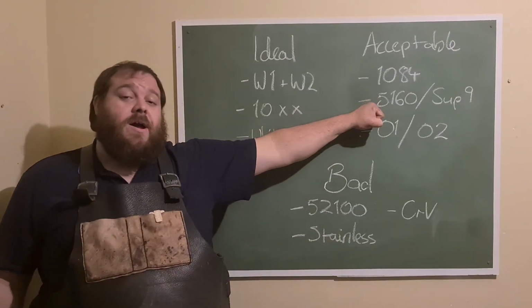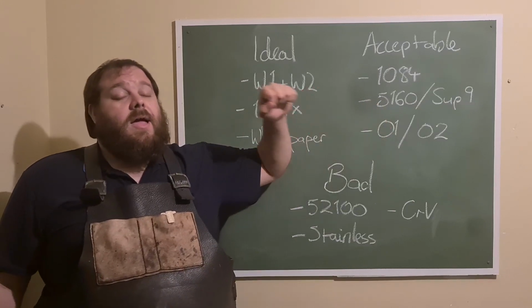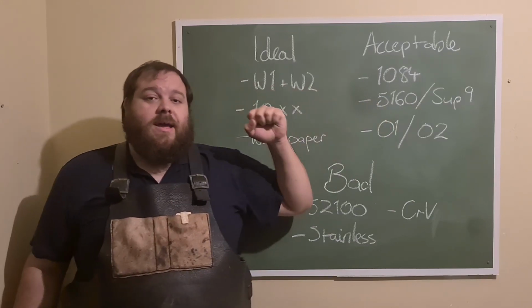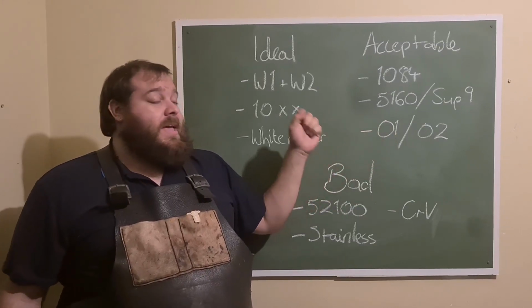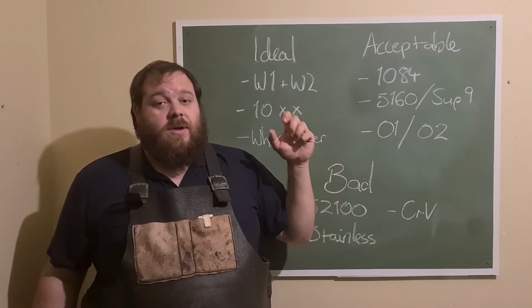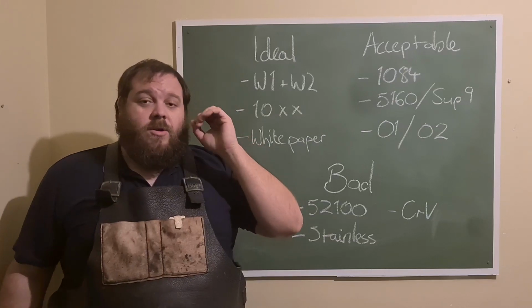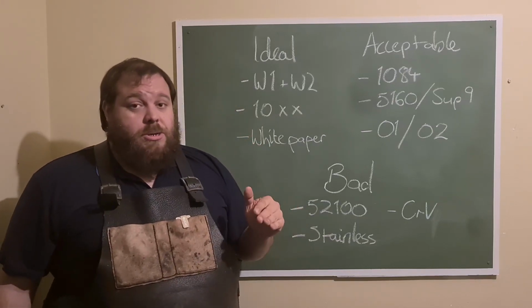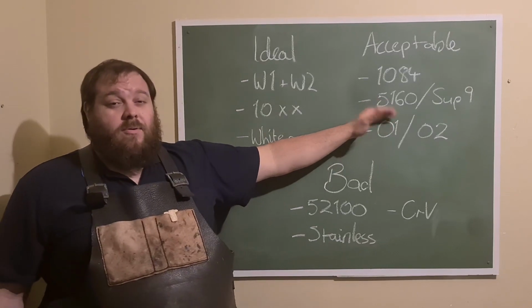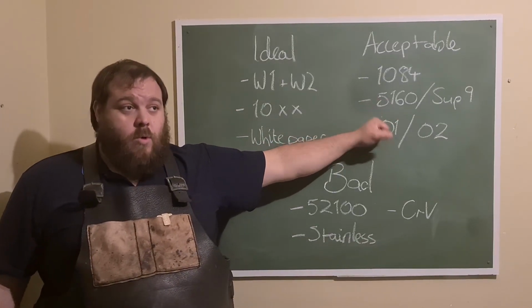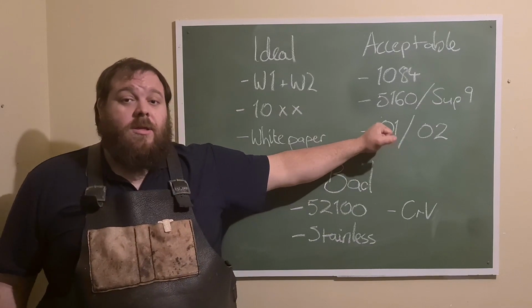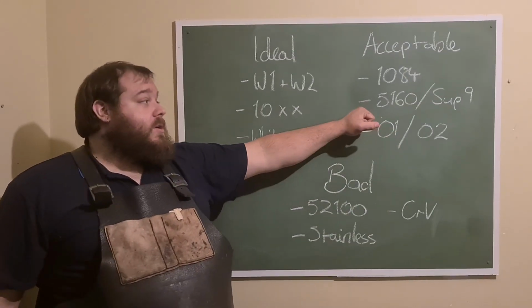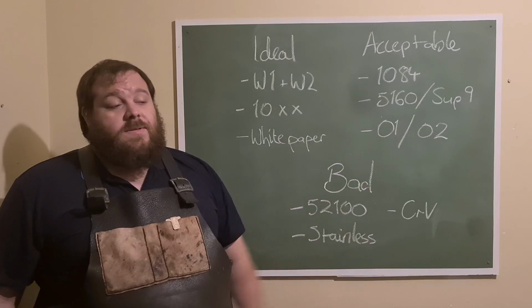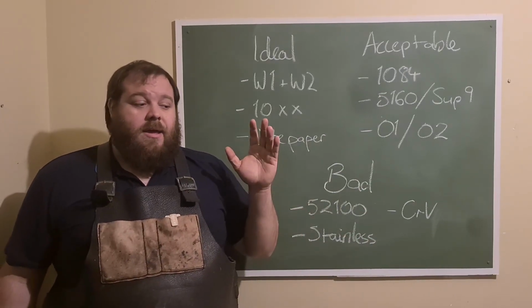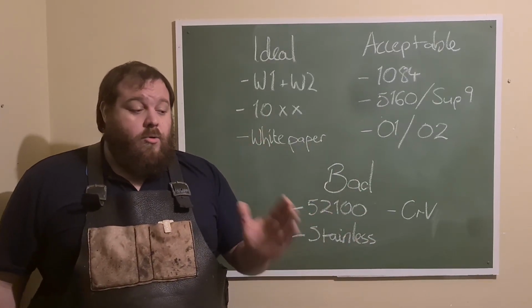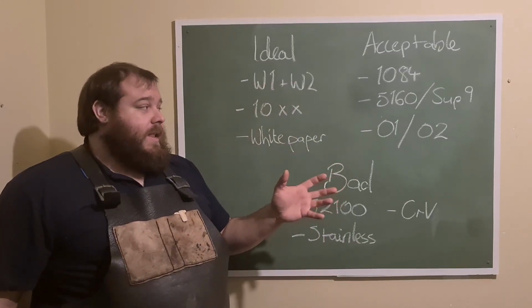5160 and Sup 9. This one surprises some people because it is a chromium steel. And the big thing is that it won't take a high activity Hamon, but it will take a nice straight Hamon. If you want to do a clean line Hamon, a differential etch Hamon or a differential quench Hamon, then you'll actually get a pretty decent one out of 5160 if you work the grain correctly. If the grain is nice and small and you get really good heat treat on it, you will get a decent Hamon out of 5160, especially if you do an interrupted quench and only an edge quench rather than doing the clay.